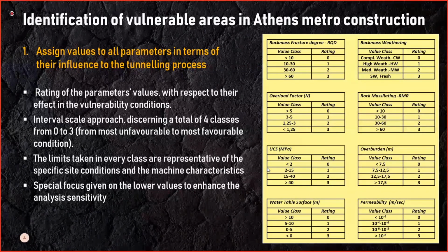In order to do so, we have selected an interval classification type, taking values from 0 to 3, from the worst to the best condition. That denotes that 0 is an adverse condition to cope with, and 3 is a very favorable one. And of course, these ratings are adjusted to take into account the construction process, in our case, the double shield TBM. If a different construction approach was to be used, then of course we would need to adjust these ratings to cater for the characteristics and individual qualities of the construction method. Furthermore, in order to enhance the resolution of the analysis in poorer conditions, special focus was given to the lower values of the classes. For example, you can see in the RQD, in the upper left corner, that special emphasis is paid to values lower than 60.